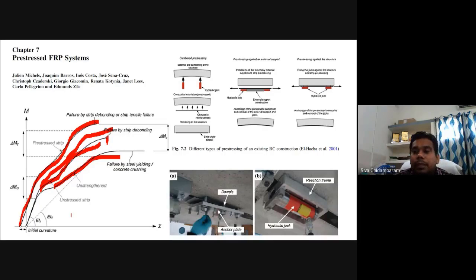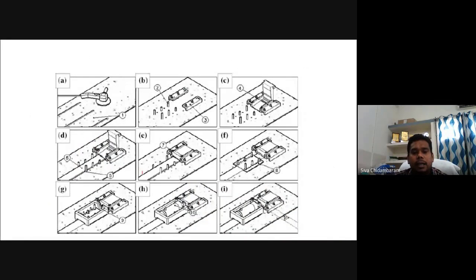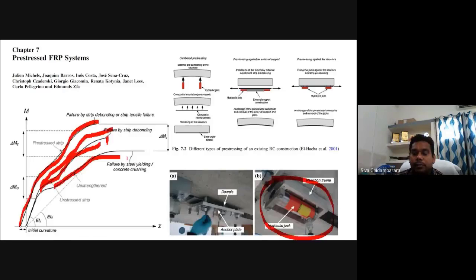When you apply a pre-stress, it is the same kind of pre-stressed concrete principle, but we are using FRP instead of normal pre-stressing strands. This is the instrumentation used to pre-stress. We have to make the anchors, and FRP plates will be placed with epoxy, and then there will be a jack. The jack will be used to pull the FRP to a certain extent. Using the pressure gauge, we will measure the applied pressure, and then it will be stuck together and anchored. This particular part is for anchoring purpose. This is for applying the pre-stress.